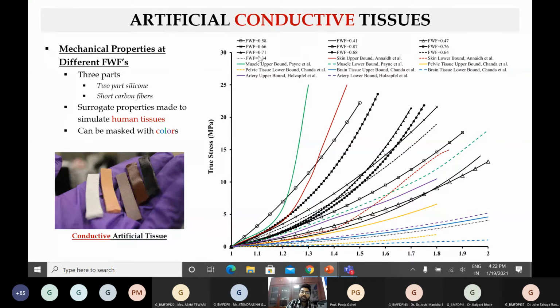These are all the specimens built with the same matrix, but different fiber weight fractions of the short carbon fibers. And the short carbon fibers are also at a very specific length, which we found as part of this research: if it is below a certain length, the crosslinks are not enough, and if it is above a certain length, it is not really desirable. So the length was also optimized. Now we are comparing all the material properties, the stress versus strain, with skin, muscles, pelvic tissue, and whatnot, like brain tissue.